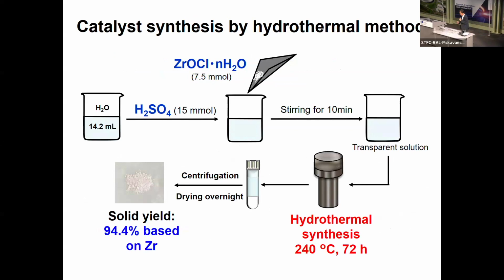Our method is very simple. You just prepare the sulfuric acid solution, add zirconium oxychloride into it, and dissolve it. After 10 minutes, you will get a transparent solution. Very easy. Then you can start hydrothermal synthesis at 240 degrees Celsius for 72 hours.